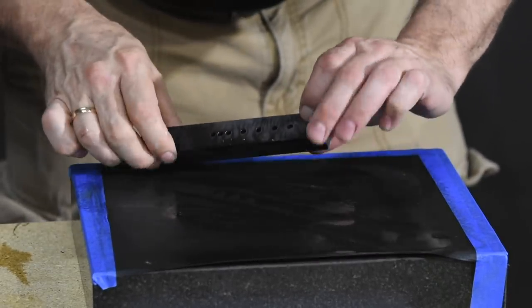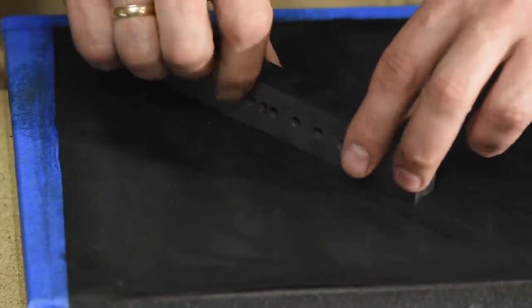After tempering, I'll clean the scale off with sandpaper. This reveals that the guide warped a tiny little bit, a pretty common thing to happen during heat treating. Now the warp only amounted to around a thousandth of an inch across the entire guide, so this wasn't a problem to remove with sandpaper.